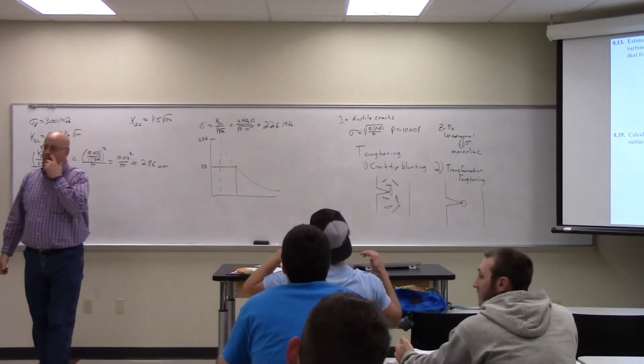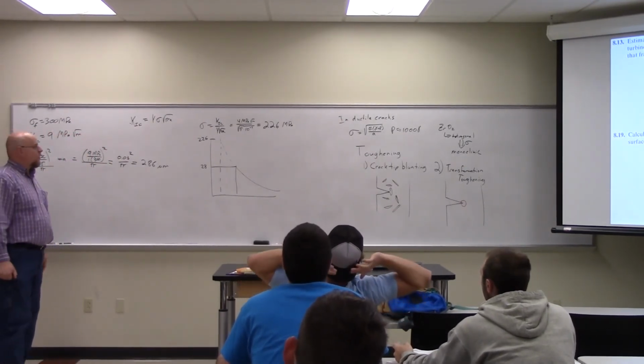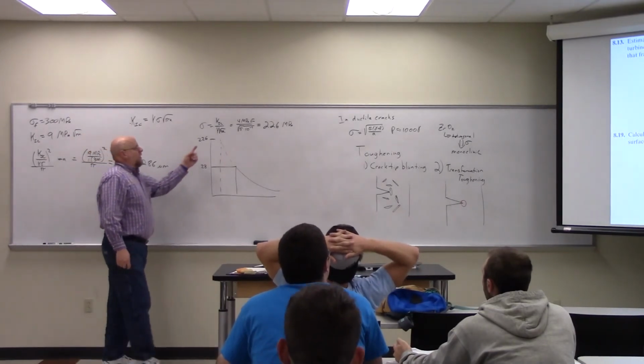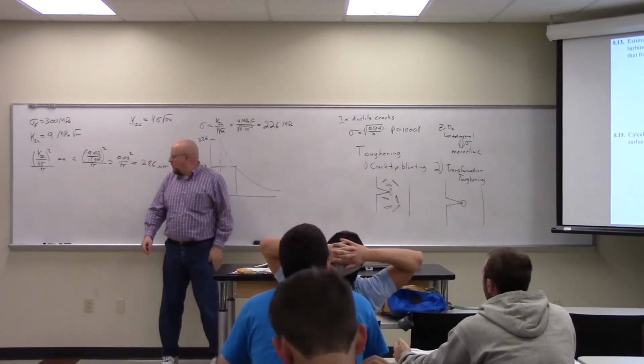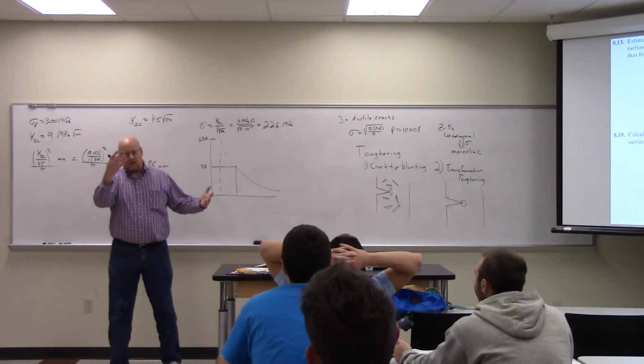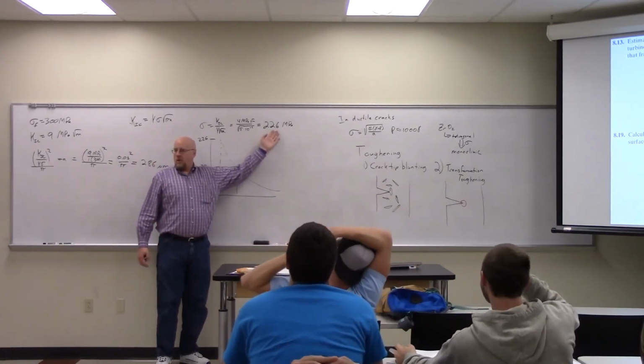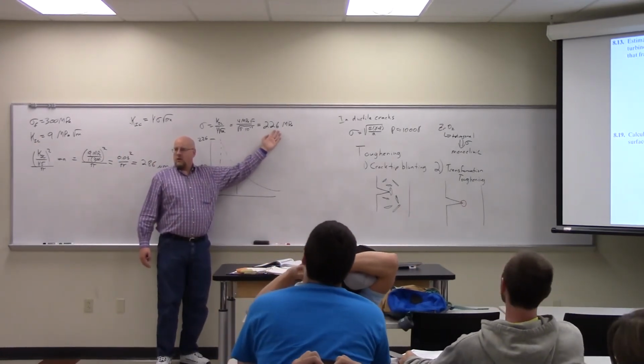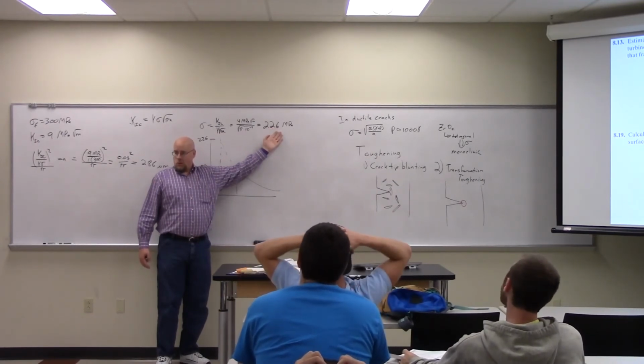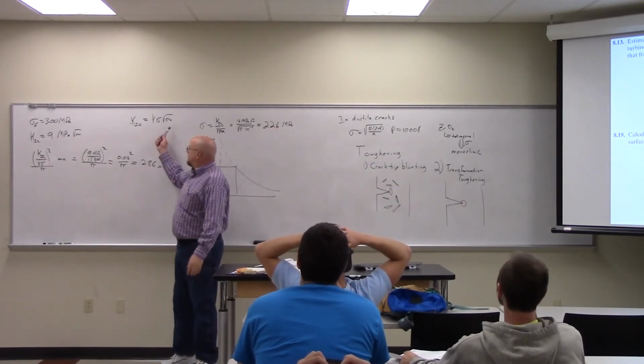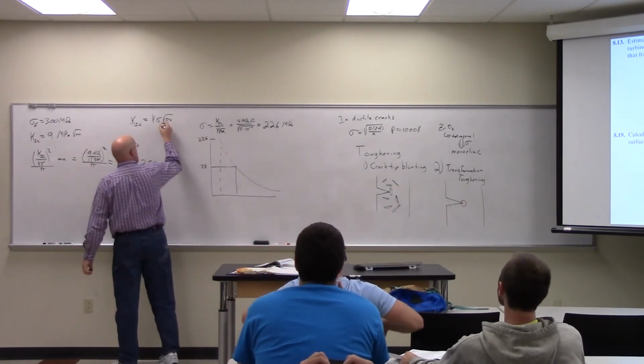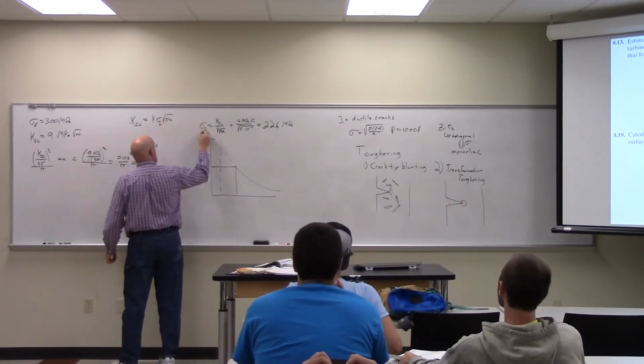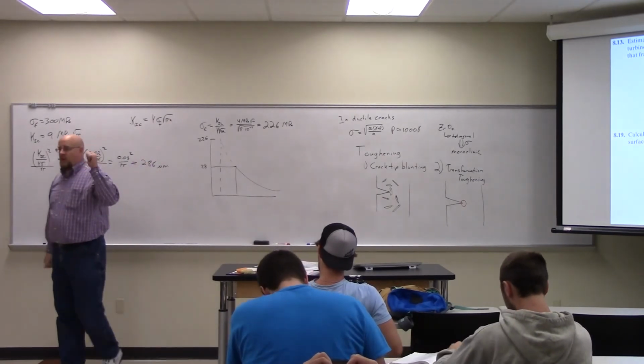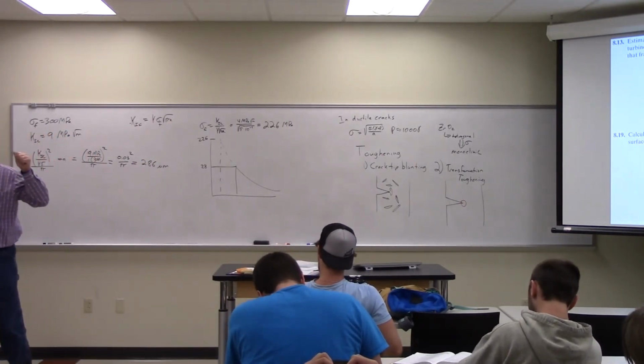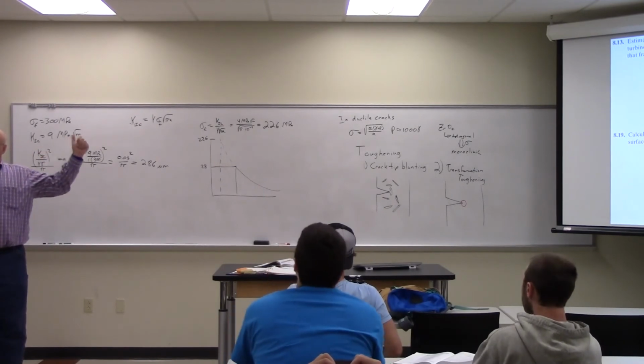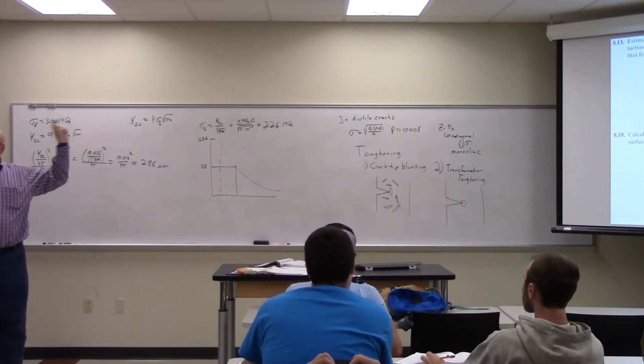So just to be clear, the sigma that you calculated is the actual applied stress, not the stress at the crack. Right, this is the macro stress, the applied stress necessary to fail the material, not sigma max at the crack. I should have written an F on here to be clearer. That sigma F is the stress at which the material will fail due to fracture caused by a crack of length A.